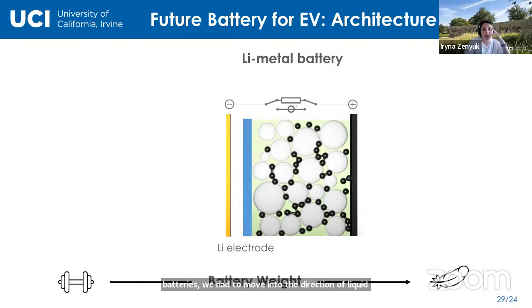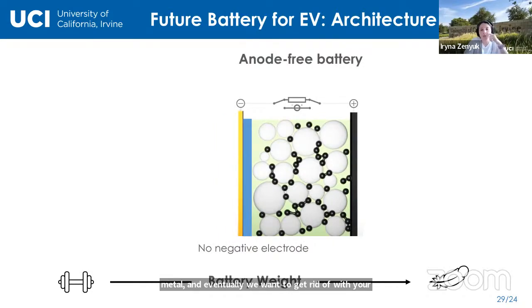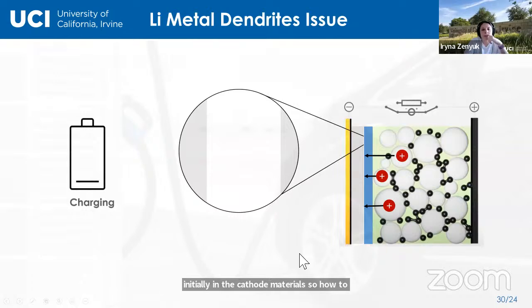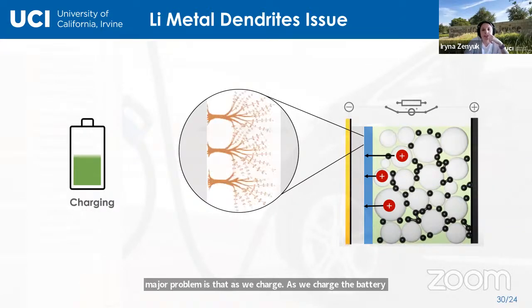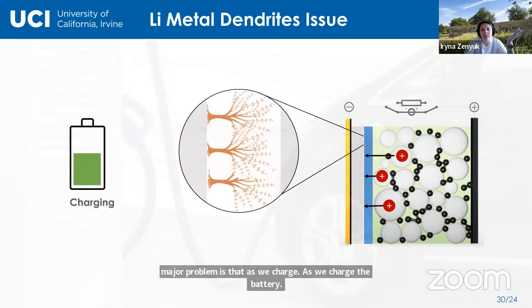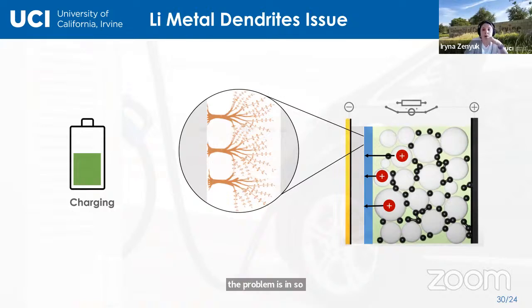And eventually we want to get rid of lithium metal and have the lithium metal free type of anode batteries, where all the lithium is stored initially in the cathode material. So how to achieve that? Well, the major problem is that as we charge the battery, we form these trees at the interface, which are called dendrites, and this is the problem in solid state batteries, whether you have polymer or some ceramic type of separator. Those dendrites will be growing on lithium metal. So there is a lot of science currently of how to stabilize this interface.